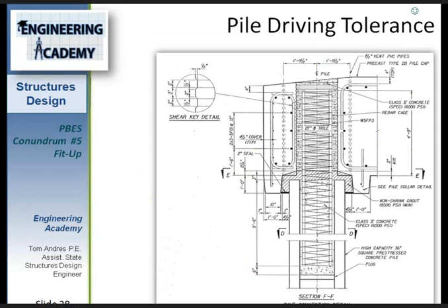Okay, here's a successful pier cap to pile connection detail, which accommodates the plus or minus 3-inch pile placement tolerance. You can see the pocket there between the pile and the precast element. It does accommodate the pile tolerances. A few other things to note about the detail aside from the pile tolerances issue include, first of all, it looks like this is a moment splice for a water project, more likely a ship impact job. So you've got to make sure that connection works in full moment. I will also note, if you look closely, you can see that the concrete is actually done in two steps. You first have the non-shrink grout, which locks the pile to the precast element, and then you have a second concrete element, which actually fills that whole socket.